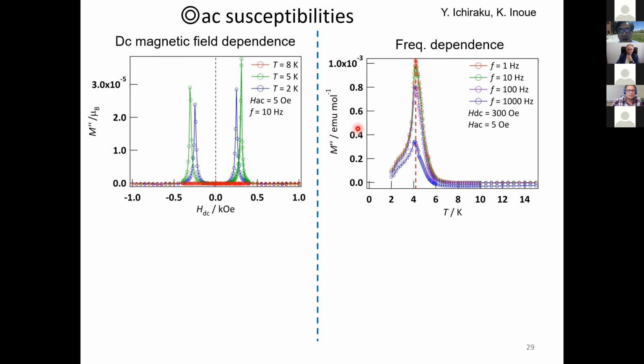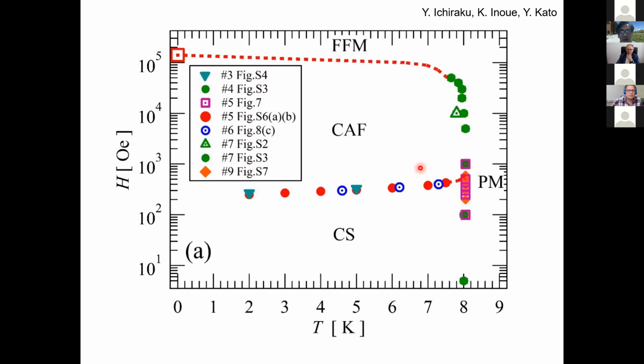This is chi double prime, and this is the frequency dependence. Here, this anomaly has no frequency dependence. Then this does not reflect spin dynamics. This is a phase transition. Then finally, this is the total phase diagram of this sample. Here is the paramagnetic phase, and TN is 8 Kelvin, and this axis is the magnetic field. This line, which I already put before, is the phase transition between one spin ordered phase and the other spin ordered phase. But if we apply more than 10 Tesla, about 15 Tesla, they go to a forced ferromagnetic state.